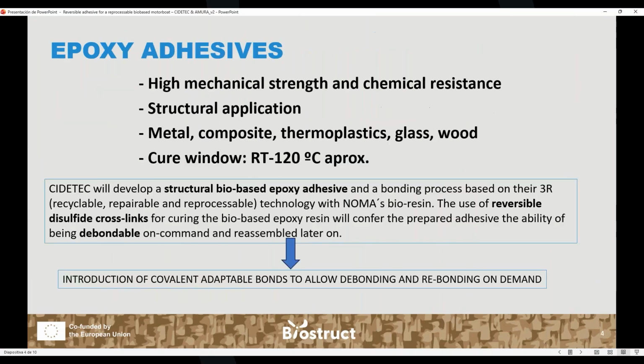Okay, so for the development of this debondable adhesive, in the BioStruct project, we have developed an epoxy-based adhesive. Why an epoxy-based adhesive? Because it is well known that epoxy adhesives offer high mechanical and chemical properties. They are highly used for structural applications. They are suitable for joining metal, composite, thermoplastic, glass, or wood substrates. And their curing window spans from room temperature up to approximately 120 degrees.